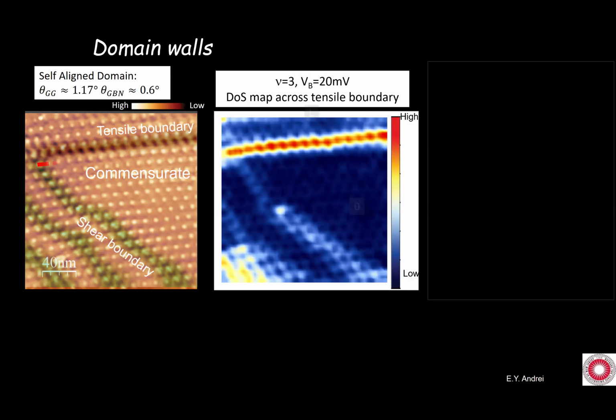So now we're going to look at the density of state map. We're looking in this region here at filling of 3. That's where the anomalous quantum Hall effect was observed. The bias voltage is 20 millivolts, and we do a map here. And you see that in the commensurate region, it's completely dark, it is gapped. And we have a one-dimensional edge state here, a conducting state. Now, a very important point here: this state is one line below the boundary of the sample. So just at the edge of the sample, at the boundary, we don't have anything.